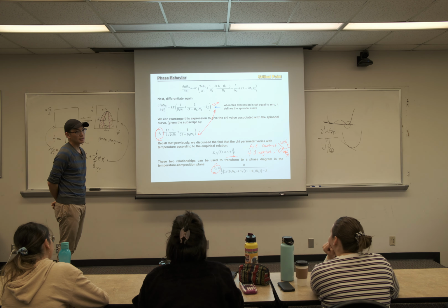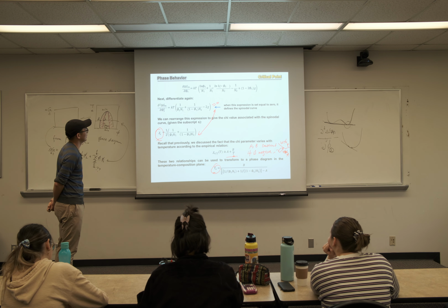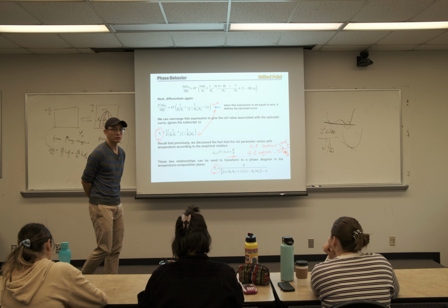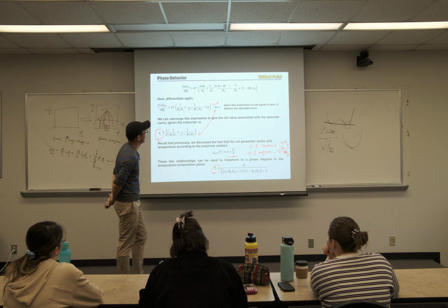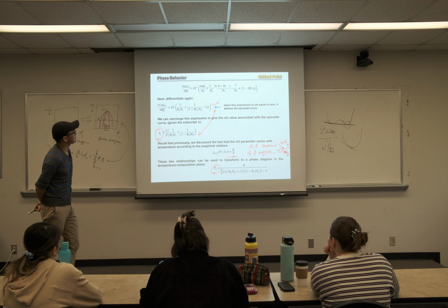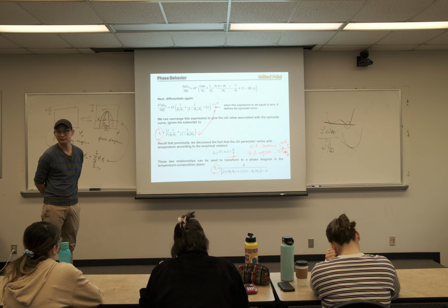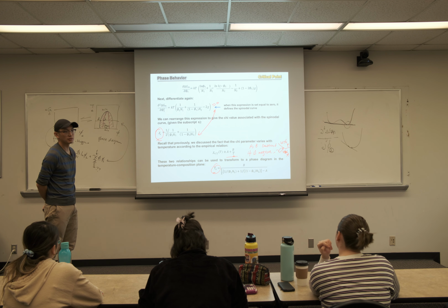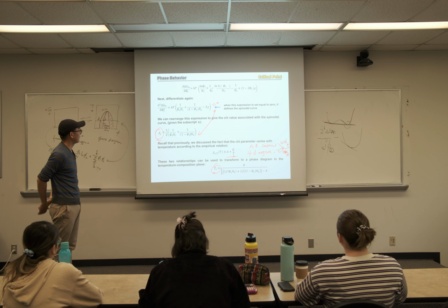Phi 1 is the solvent's concentration, N1 and N2 are the degree of polymerization for your solvent and for your polymer, and this is how it depends on the chi. So when this expression equals 0, this defines your spinodal curve. Right? Second derivative equal to 0 is when you have a concave up or concave down transition.